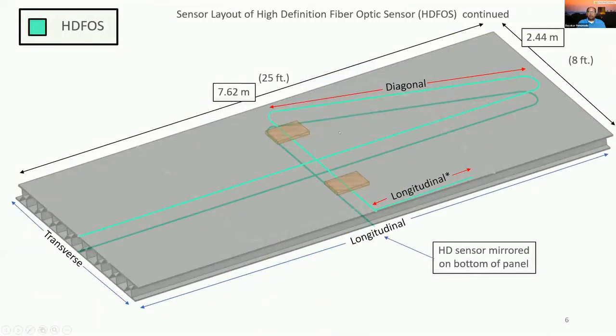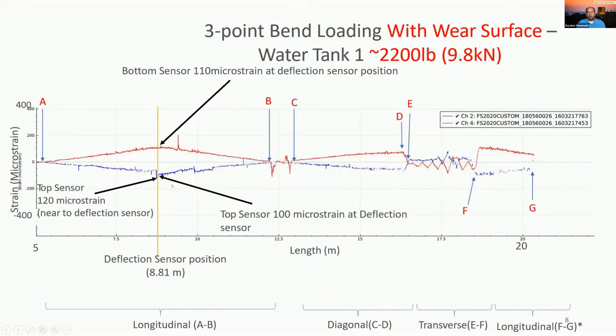And if you were to see a rendering of this, you can kind of see in 3 dimensions where we laid out the various types of sensors and load points, if you will. And this is the kind of data you end up getting. So for example, if we had unsupported deck except at the edges, so we have a nice point load system. And if you just focus here on the A to B panel width, roughly this is about 6 meters spacing. We got hundreds of strain gauge sensors from that one fiber optic continuous sensor. And you can see very beautifully that on compression and tension side, you have expected linear strain with a maximum strain corresponding to the peak bending moment at the load point.